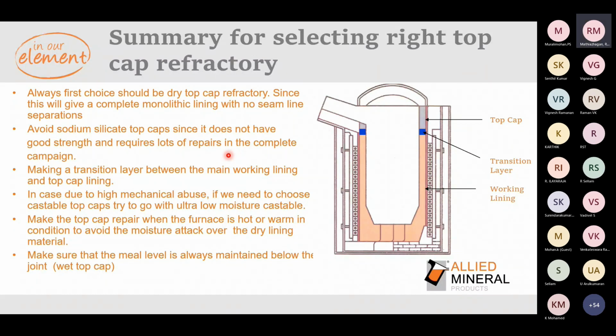As shown in the picture, whenever you're going with the dry top caps, make a transition layer. Take one bag of the main working material and one bag of top cap material, mix it, and put one layer where the blue has been indicated. That's a transition layer. Once that has been done, then you can go with the complete top cap material on the top.